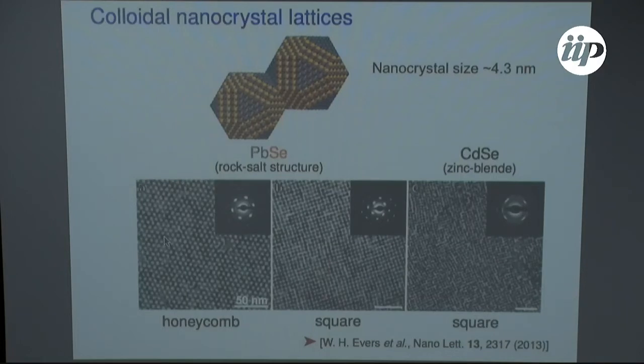They get rid of all the lead and replace it with cadmium. So they get a honeycomb crystal, very large, made of cadmium selenide. It's funny because this has a different structure: one is rock salt, the other is zinc blende. But you can show that you replace everybody. But then comes the question, as a theoretician, you would ask: if I make a honeycomb of semiconductors, does it behave like graphene, or does it behave like the constituting blocks, the semiconductors? And that's what we went on to calculate. And the answer is both.